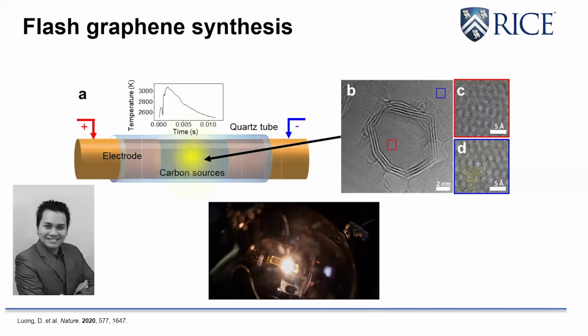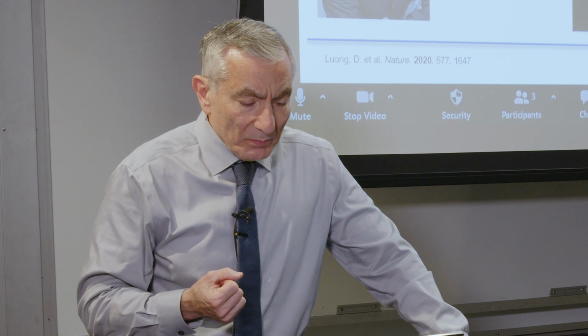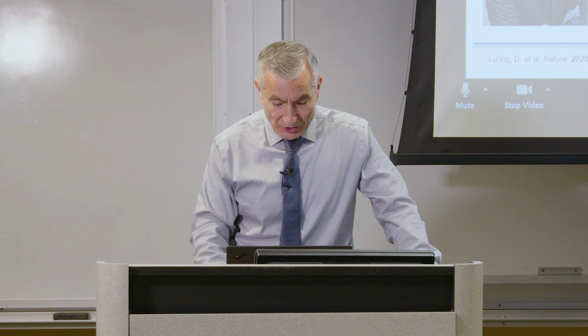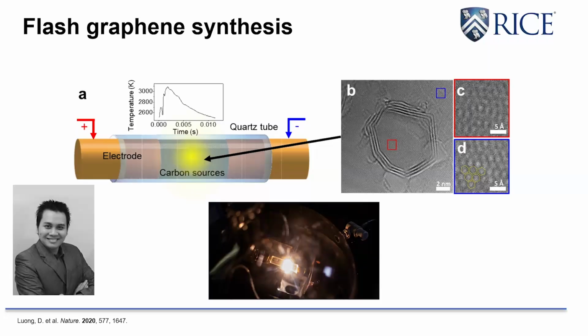A furnace would make this such that you have to heat a big furnace and keep this thing hot. This is a lot of energy, but for a very short amount of time. So it turns out that the amount of energy that you're actually putting into the sample is overall very little. It's a lot, but over a very short time span. And you get this big flash, and that's why we named it flash graphene, because for something to take off, you want a good catchy name. And flash graphene, it gives flash, and people will think about it, the flash graphene synthesis.